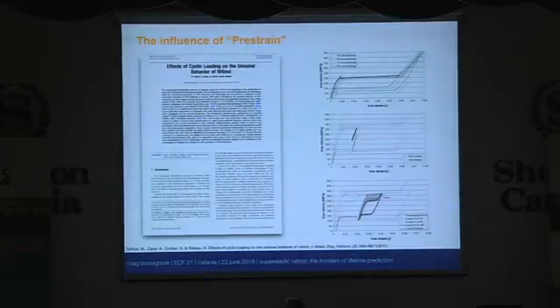here, and let's look at pre-strain. This is some work that we are doing back in California, and we are beginning to understand that pre-strain is something that has a big influence on fatigue performance of these materials. And it's been studied and published, but the gist of it is the more strain you put into your device, it changes your plateaus. So the higher you go up on this curve, when you come back down, your curves are dropping. So your plateaus are dropping. The material is changing as a function of its strain history.